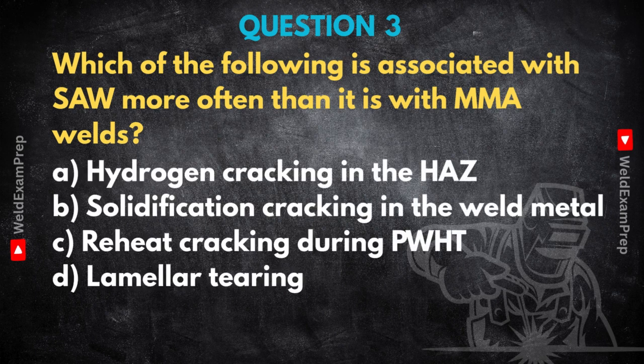So think about submerged arc welding, SAW, compared to manual metal arc, MMA, or stick welding. What kind of cracking is associated more often with SAW than with MMA? Are we talking hydrogen cracking in the HAZ, solidification cracking in the weld metal, maybe reheat cracking during post-weld heat treatment, or lamellar tearing? The one most specifically associated with SAW, more so than MMA in this context, is solidification cracking in the weld metal.